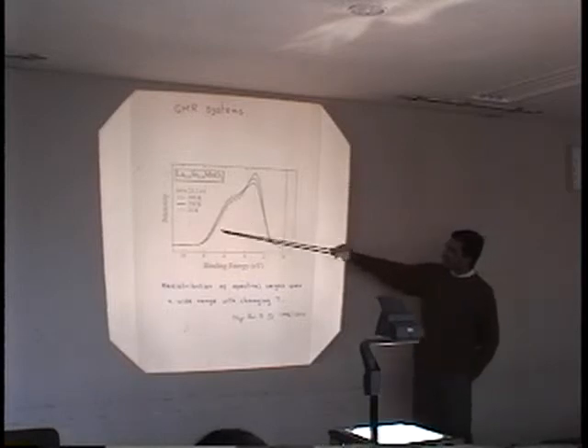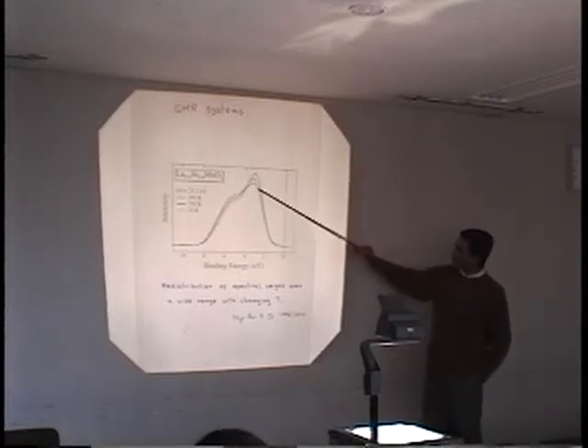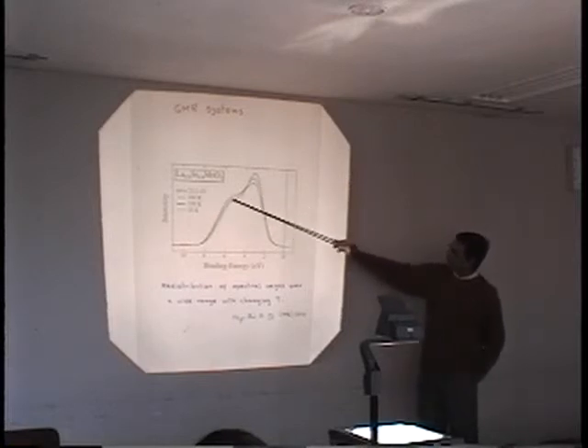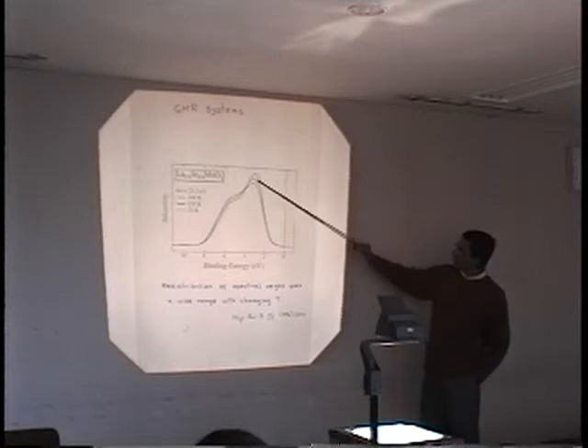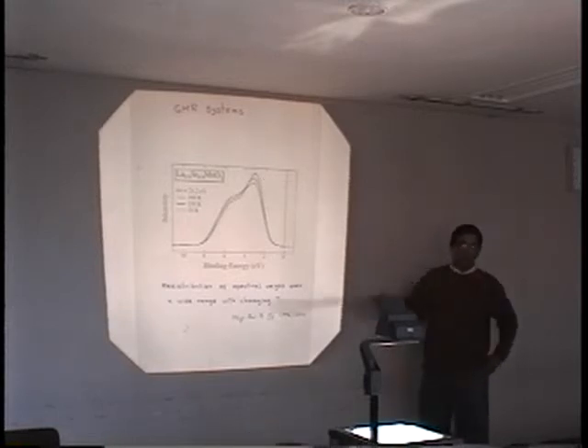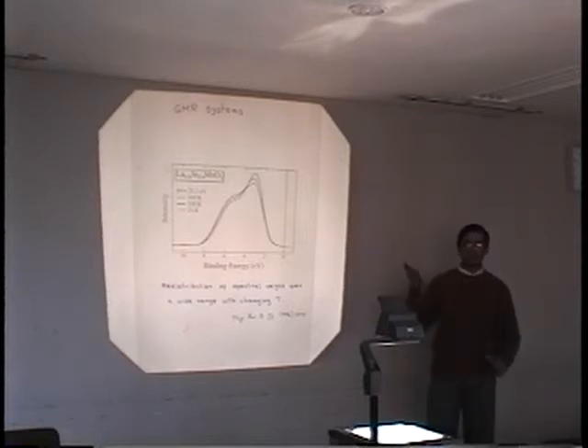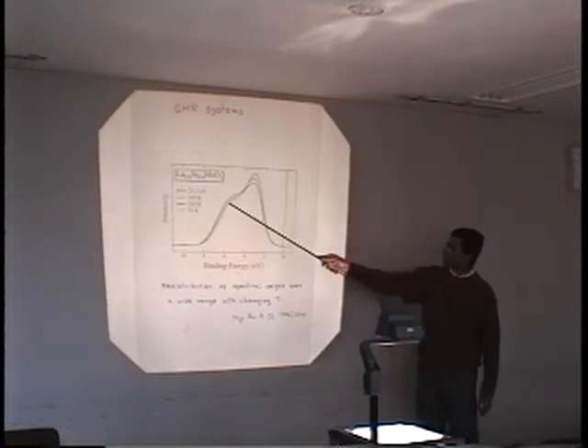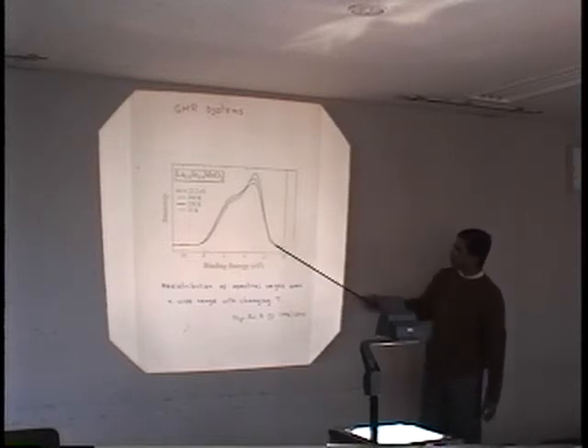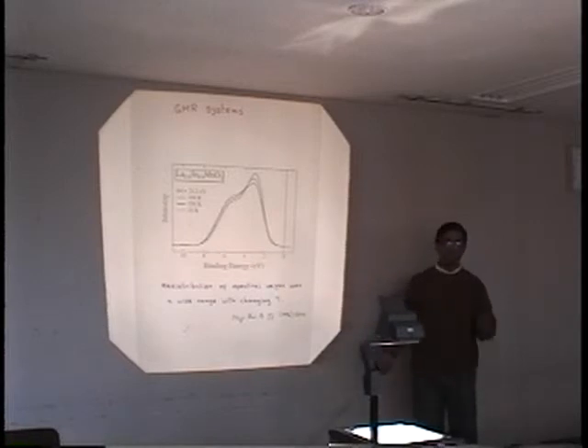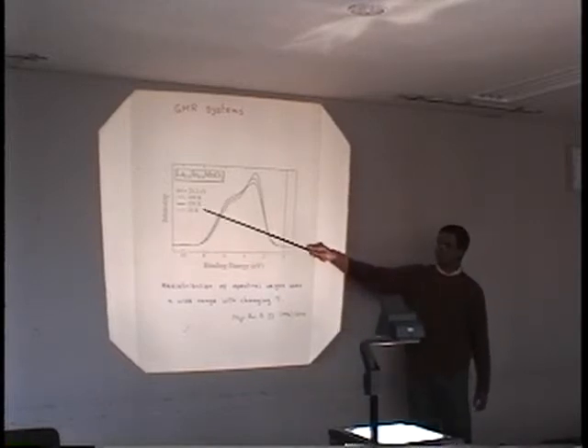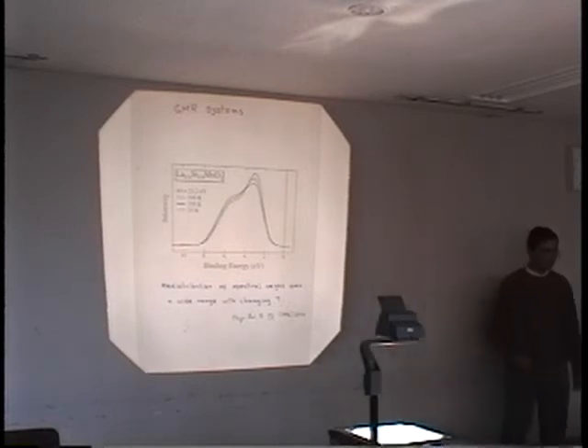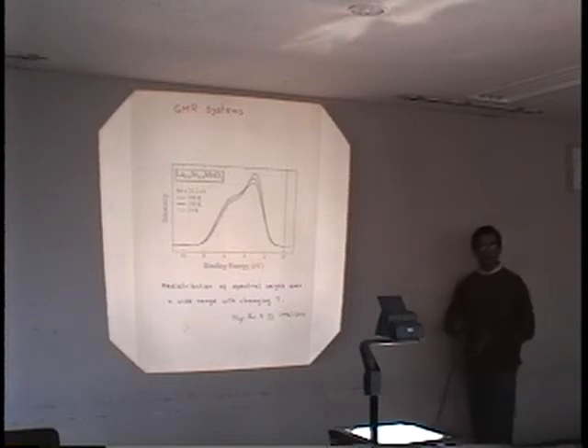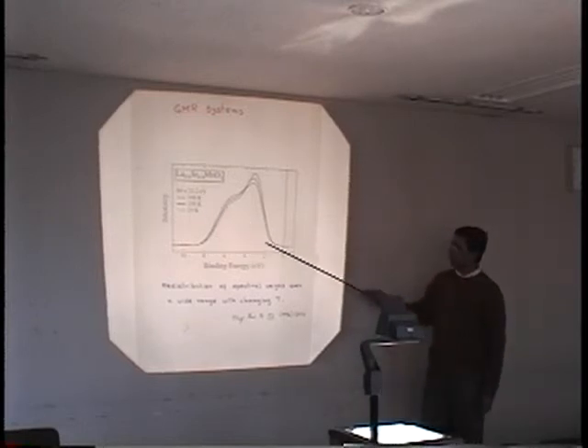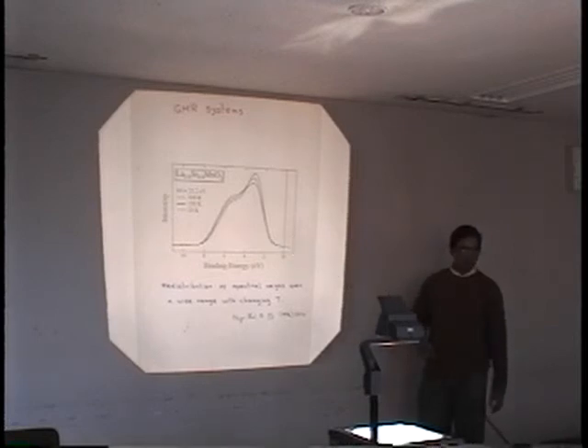You find that at the lowest temperature, this black spectrum. As you increase the temperature, you lose intensity from this region and transfer weight in this region. This is a very surprising phenomenon. This is not seen in any other system. That you have spectral weight transfer over several electron volts. Remember, the spectral weight transfer is taking place over an energy range of 8 electron volts. The thermal energy is in the order of tens of milli-electron volt. So there are several orders of magnitude difference between the thermal energy and the energy over which spectral weight is being redistributed. And this is something I must admit we do not fully understand.